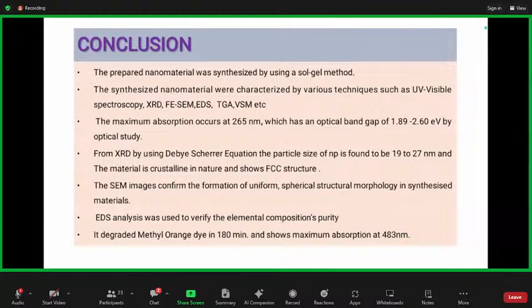The maximum absorption occurs at 265 nanometer, which has an optical band gap of 1.89 to 2.60 electron volt. From XRD, by using the Scherrer equation, the particle size of the nanoparticles is found to be 19 to 27 nanometer, and the material is crystalline in nature and shows FCC structure. Then, from the SEM image, we confirm the formation of uniform spherical morphology in the synthesized material, and EDS analysis was used to verify the elemental composition purity.